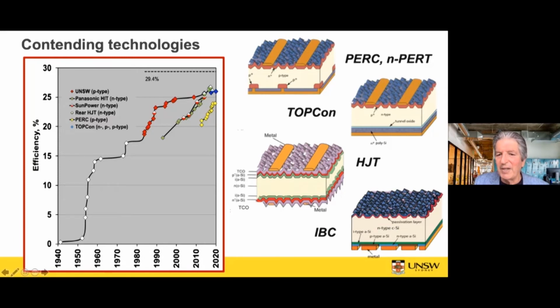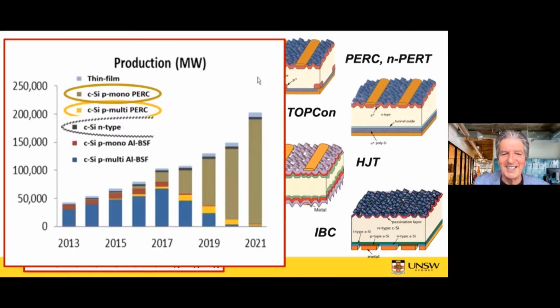And then the bottom structure is the interdigitated back contact structure, which has both contacts on the rear, which is good because the top contacts tend to shade the top of the cell, so you put them on the rear, you've eliminated that loss mechanism. That's in fact the oldest of those structures, so it was invented or first suggested in 1977, and the others in the 1980s.